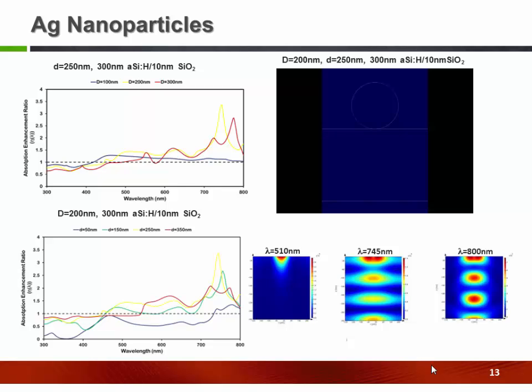The behavior was also investigated by changing the distance between the particles, and we see that for both cases we have an optimum parameter. These are the two parameters that we can obtain, and we could observe the absorption at the interface of the layer at different wavelengths to investigate the mechanism as well.